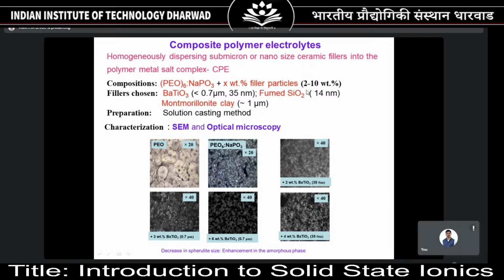Again, here you can play with different weight percent, because there is always a limit with composites. Everybody is aware that only up to a certain level can we have the fillers. After that, there will be a blocking effect. No more is the original property of the matrix retained. Our aim is to enhance the properties of the original matrix.